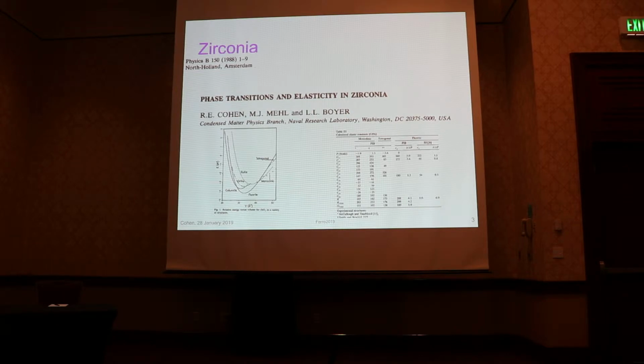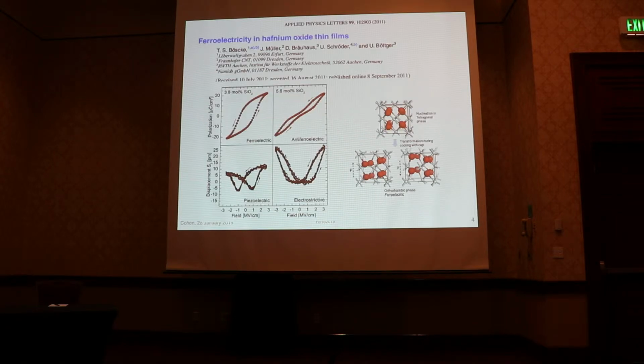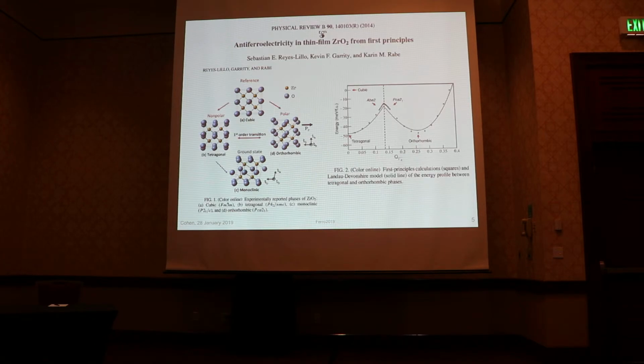And almost everything about it is strange. And one of the things that I did right back then was try to understand the elasticity of this material, which was a whole other story that I'm not even going to get into today. So in 2011, and maybe there were earlier papers that talked about this as well, it became clear that there was ferroelectricity in thin films of Hafnia, and they were quite nicely measured properties, but also sometimes it was anti-ferroelectric depending on the composition. And even then, it became clear that there were these different phases, a tetragonal phase and an orthorhombic phase that seemed to be ferroelectric, and it was all very intriguing and very interesting.